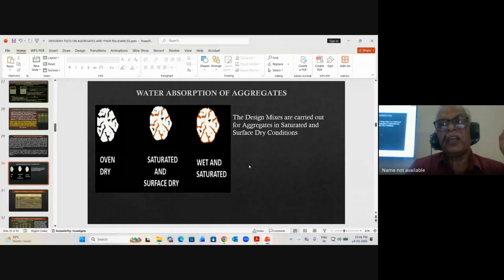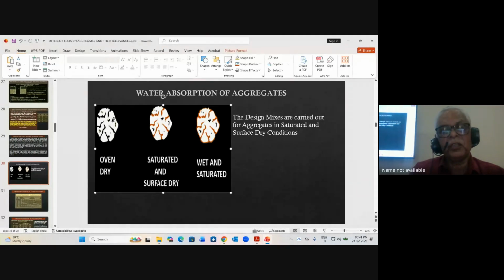change because of specific gravity and water losses. In design mixes, we are considering 3 types: oven dry, saturated, and surface dry. The first one is oven dry - there is no moisture, neither inside the aggregate nor outside. In saturated, there is moisture fully saturated, but there is no moisture on the surface of the aggregate. Then wet and saturated aggregate. For design mixes, we are considering only saturated and surface dry concrete. So this is very, very important.